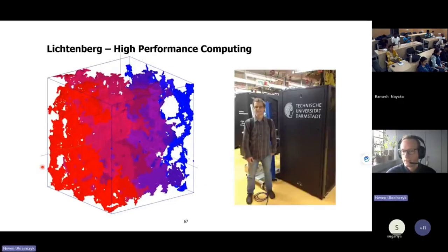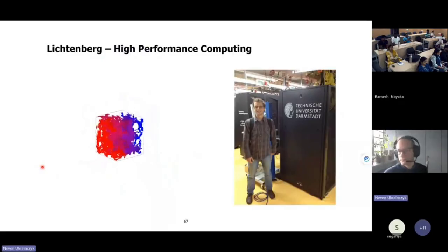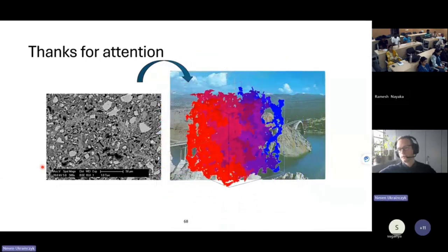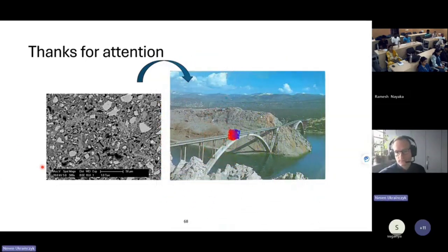So again, some conclusions, and here now I'm doing the modeling using a supercomputer for these acid models. And here I would like to finish by linking everything together. You need the microstructure, which was the first day. You need pozzolanic reactions, to adapt the models for the current modern binders, which are clay or even geopolymers. You need to understand the microstructure formation, and then it's important also for the durability. And again, you have this multi-scale approach that you should go from microstructure, from the chemistry, from raw materials to the structure, and to be able to predict the performance at the structural level.